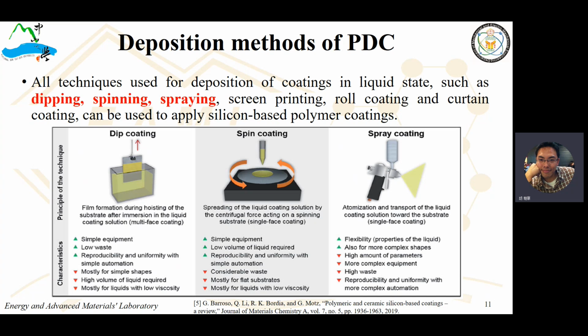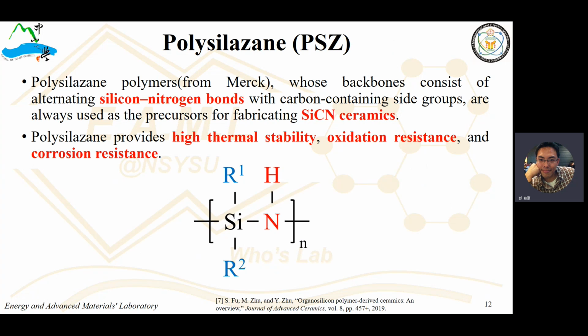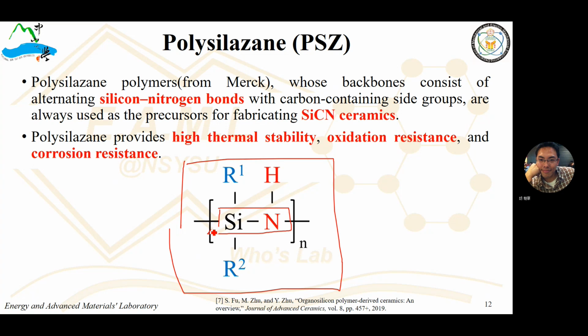For the coating techniques of PDC, the techniques include dip coating, spin coating, spray coating, and so on. It depends on what kind of surface you have. If the surface is not uniform, with a complex shape, maybe spray coating is the optimum technique for a uniform coating on a complex surface. If the surface is porous, maybe dip coating is more suitable. And the polysilazane pre-ceramic precursor is commercially available from Merck. Its chemical structure, as I already mentioned, has the silicon-nitrogen bond with different functional groups and contains hydrogen.